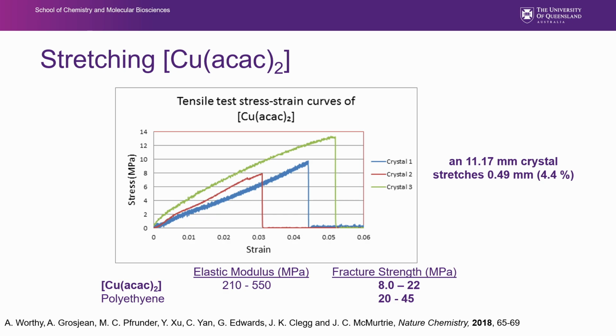So here are 3 different crystals, and we've just measured them in our tensile testing machine, and you'll see they're all nice and linear until you break them at some point, and they catastrophically fail. What you get from the slope of these curves is an elastic modulus and a fracture strength. And so what we see here is that the fracture strength is almost the same as polyethylene, so the material that's in plastic bags. So very interesting.